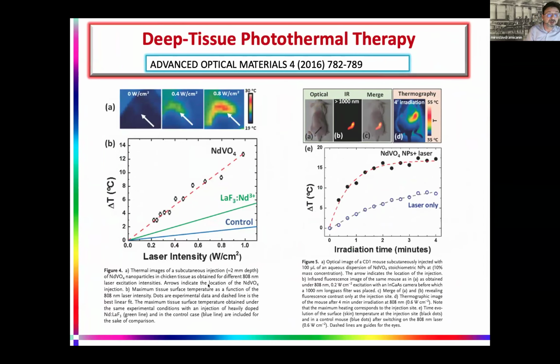We did this research with the famous group of Professor Daniel Jacques because there are many things that we could not do, in vivo measurements with small animals. That's the main reason, and he has all the facilities and huge knowledge to perform this. So let me go to this part of the experiment. We injected our nanoparticles, and lanthanum fluoride nanoparticles were kind of standard until we showed results with this type of nanoparticles. As you can see, the temperature generated by our nanoparticles is much higher for the same laser intensity that we put on the tissue.